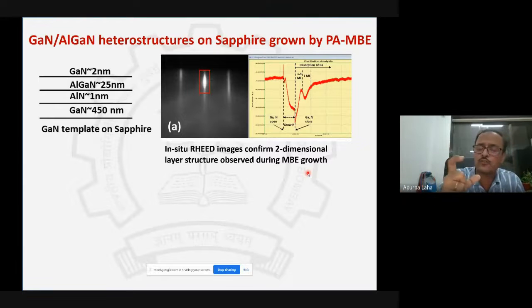Now, the time it takes to regain the intensity will tell us the percentage, or how many monolayers of gallium you have on the surface. So it's an atomic layer precision that one has to follow in order to grow this layer. The window of this process is really narrow. For example, in terms of substrate temperature, we grow around 762, 765. It has to be 762 to 65. That's the kind of narrow window, and we fix this window with the RHEED. So it's very important to look at the RHEED and understand this.